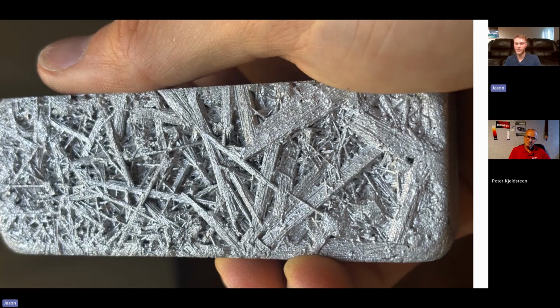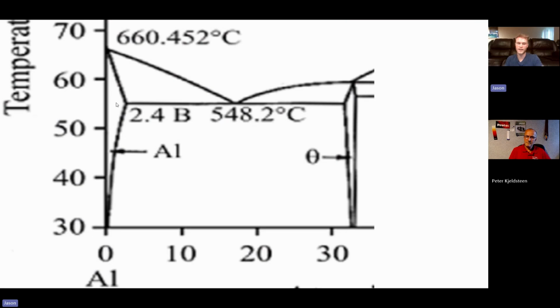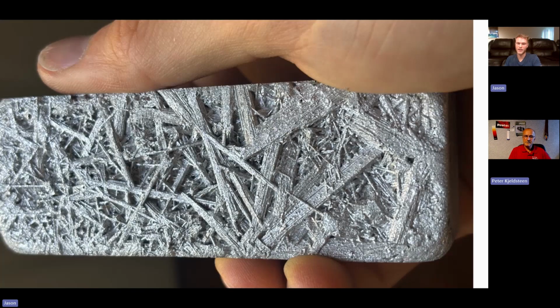You have these crystals, and then in between them, you can't see here, but in the solid, you're going to have a eutectic between the theta and the alpha. And so as we solidify and exhaust all the intermetallic stoichiometry, we move to a eutectic region where a coexistence between the alpha and theta solidify essentially at the same time. And we get a eutectic region between the two.